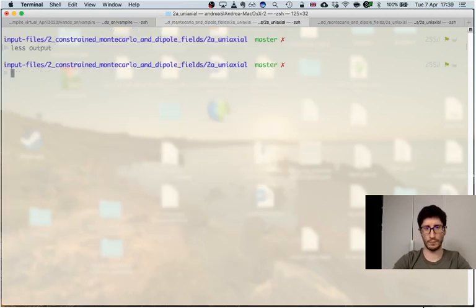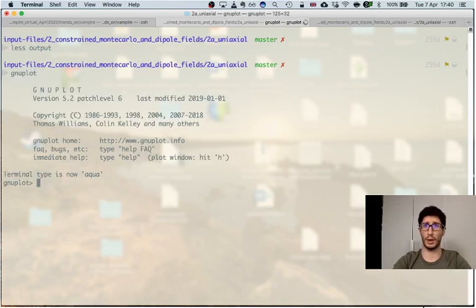So what we then want to do is to plot the torque. I will not show how to integrate, but I will tell you, as I already mentioned, we can extract it for the uniaxial case from the maximum of the torque at 45 degrees.